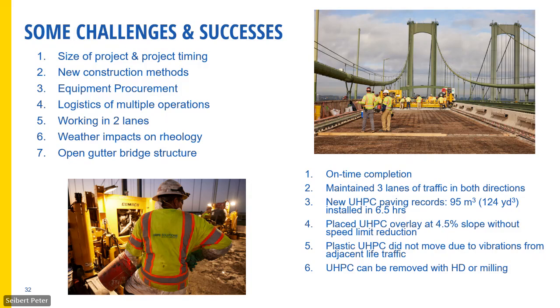Again, we were working 24 hours, 7 days a week. We had meetings day and night to coordinate all our operations. We had up to 200 people working on the job site at a time. It was a big undertaking. The weather impacts, the open gutter on the bridge, they were all significant challenges of how to overcome hydrodemolition procedures, capturing of water, lots of little things that on a small overpass are just kind of overlooked. On a big structure like this, even if it's a small thing on a small overpass, well, you magnify it by 2 miles long and it becomes a huge issue.